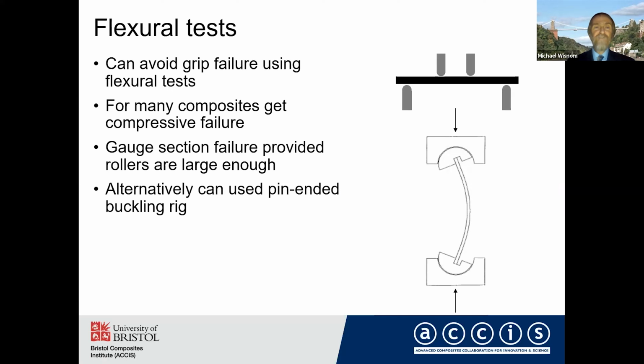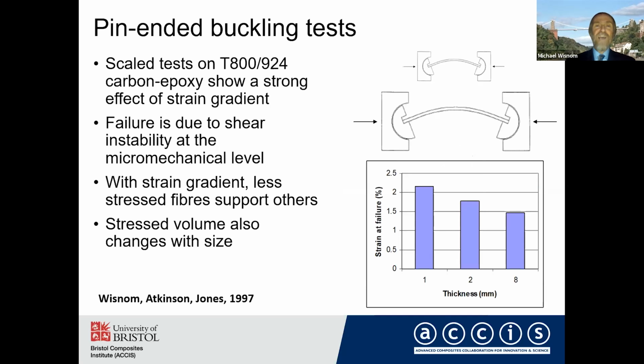Alternatively, we did tests some time ago using this pin-end buckling rig, which eliminates any issues about local contact or roller contact stresses completely. We did some scale tests on those pin-end buckling tests, where the whole thing was scaled: length, width, thickness of the specimen, and indeed the end fixtures. And what you see is a very large effect, with the strain varying from about 2.1% on the very thin 1 millimeter specimens down to 1.5% on these thicker specimens. So quite a significant effect of the size of the specimen on the compressive failure strain.